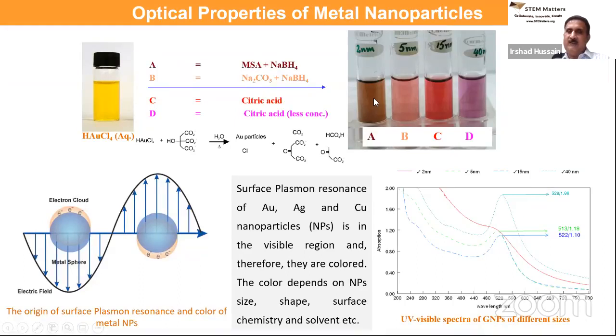But if the size is bigger than 2 nanometer, they start showing some color that could be from yellowish red to red to purple and finally blue, depending on the size of these particles. And this color is not due to electronic excitation of these particles that we normally observe in molecules, from HOMO to LUMO. That is because these particles are metallic in nature, and electrons at the surface of these particles, which are bigger than 2 nanometer, are oscillating at a certain frequency. Depending on their size, shape, and surface chemistry, they then absorb light of the wavelength that matches that oscillation frequency. That is why these particles will absorb at different wavelengths depending on their size, shape, and surface chemistry.